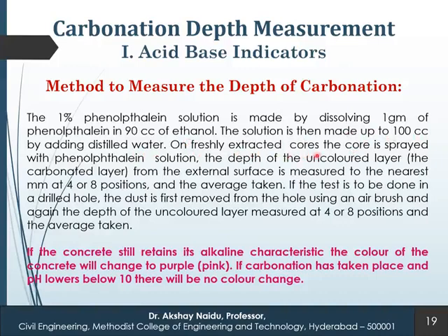On a freshly extracted core, the phenolphthalein solution is sprayed, and the depth of the uncolored layer from the external surface is measured to the nearest mm at 4 or 8 positions, and then the average is taken.